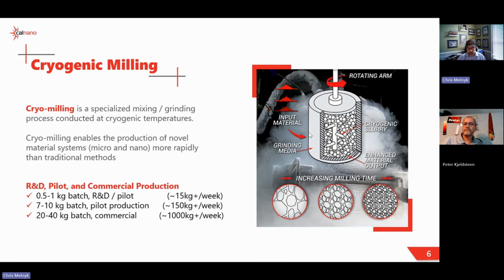And then the material you're going to process is already powdered in this case. And then we completely cool it down to cryogenic temperatures and then mix it, often, not all the time, but often completely mixed with liquid nitrogen or liquid argon. So it's in a slurry. And then it's being ground, and we're adding more liquid nitrogen or liquid argon, and then there's some being circulated in the jacket to keep it cold. Exactly.